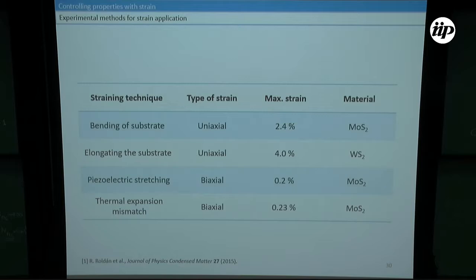But I think that for this material in particular, it might be a bit higher, because the thing that limits it is not that the substrate only increases by 4%. It's elastic, you can pull a lot. But eventually it will slip, right? The 3D material will try to keep up with the substrate that we're expanding. But eventually the strain energy will become very high, and it will slip from the substrate and will not increase its size as much as the substrate will.